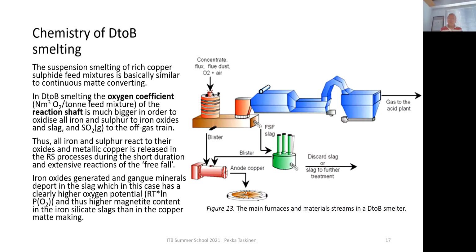And this also means that as we are producing metal copper with only some sulfur in it, our slag chemistry must be so that it dissolves all these gangue minerals, and the slag is stable. It is modified in such a way that it is stable at high oxygen partial pressures. So this is a much more tricky fluxing situation than continuous converting, for this very reason that all the